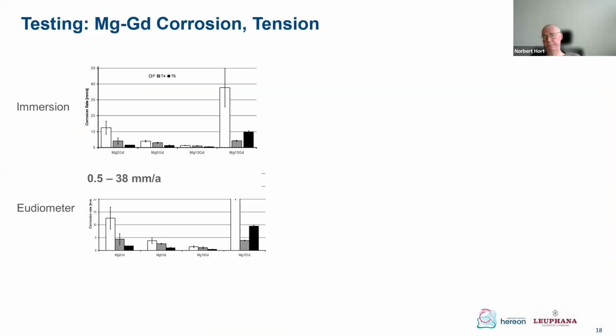Properties. When we started with magnesium gadolinium, this publication is from 2009. We saw the content of gadolinium is responsible for different corrosion rates. And again, this is based on intermetallics. So for the magnesium 10 gadolinium, it seems that we found the lowest corrosion rates, testing them by immersion and eudiometer as hydrogen generation. So we can select composition with respect, again, to what we need for the application.